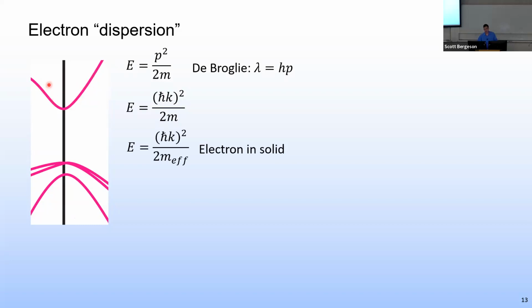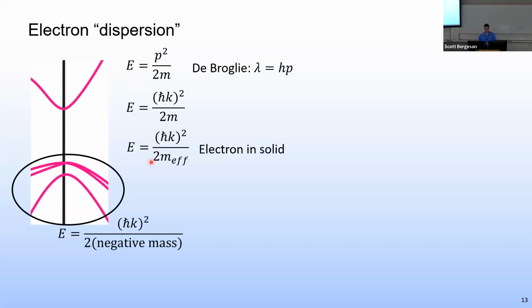The parabola that you get, however, inside your material is different than the parabola that's predicted for a free electron. And so the way we describe that is using a concept called effective mass. The effective mass describes the curvature of the parabola. If you have a small amount of curvature, you end up with a large effective mass, which means that you change the momentum by a lot, but the energy only changes by a little bit. Conversely, if you have a big curvature here, you can have a small effective mass, and then the reverse happens. So that's one way we talk about electrons in solids, is through the effective mass.